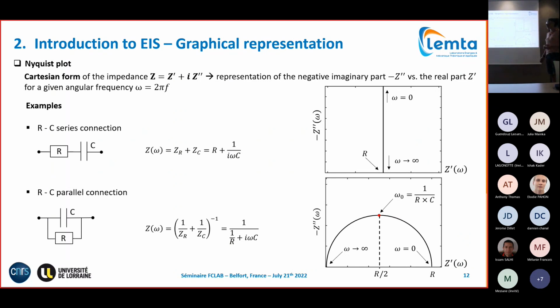The negative imaginary part is used for convenience, in order to be able to represent a Nyquist plot in positive form. Here you see an example of a Nyquist plot for a resistance and capacity series connection. The resistance is a vertical line, a purely real impedance element, which intersects the real axis at the value of this resistance. And you have a vertical line which goes to infinity for a frequency of zero, typically for a capacity.